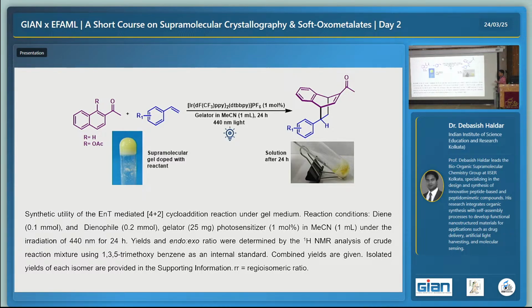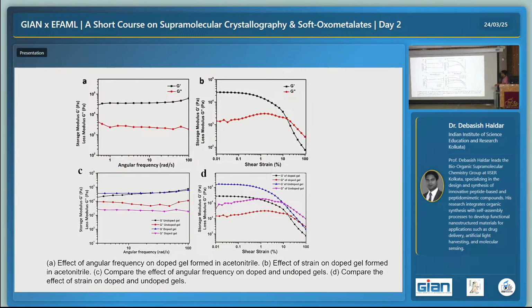So it is open air. The sensitive reaction is happening in the gel matrix, and the gel matrix is working as a confinement to do this reaction. So we have started with all the rheological systems. Before incorporation of the reagent, after incorporation of the reagent, and after the reaction, how the viscosity and rheology of